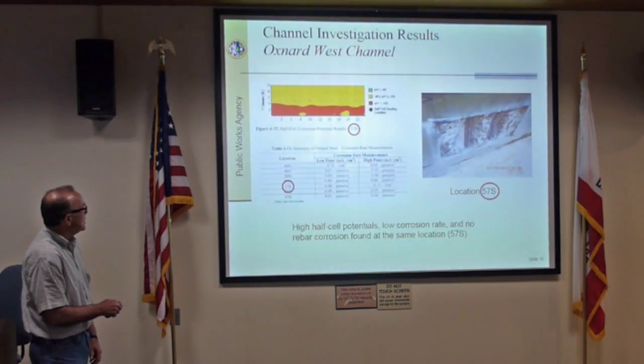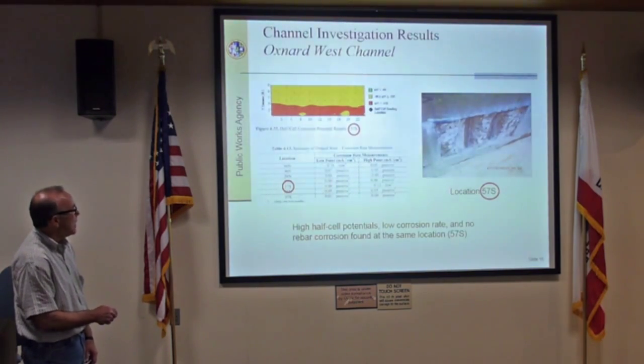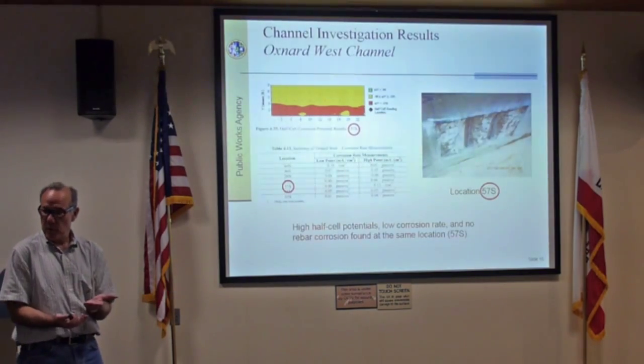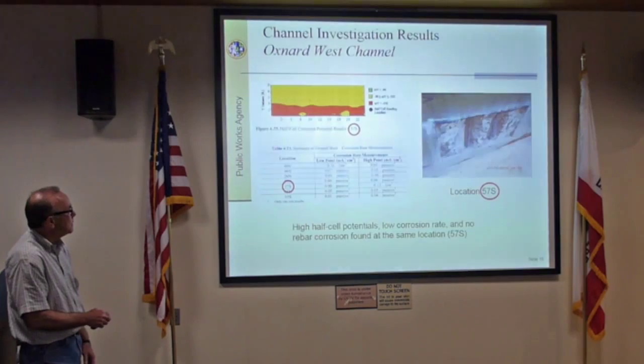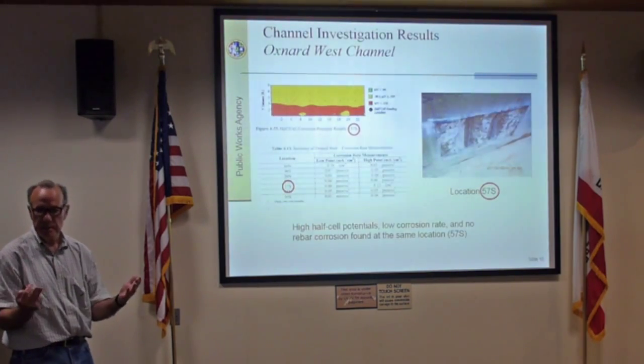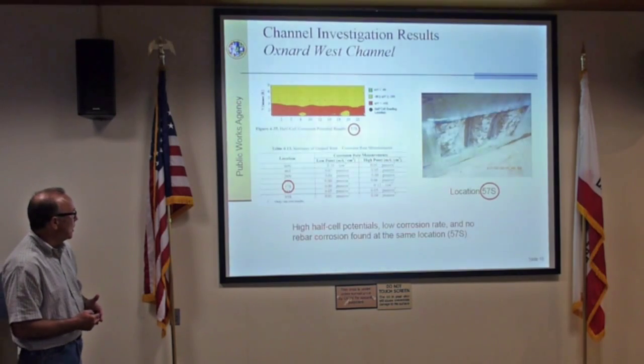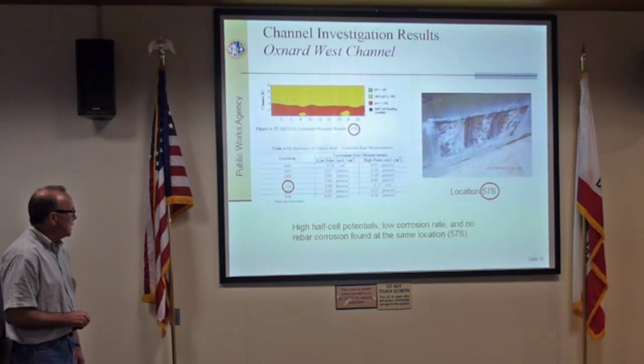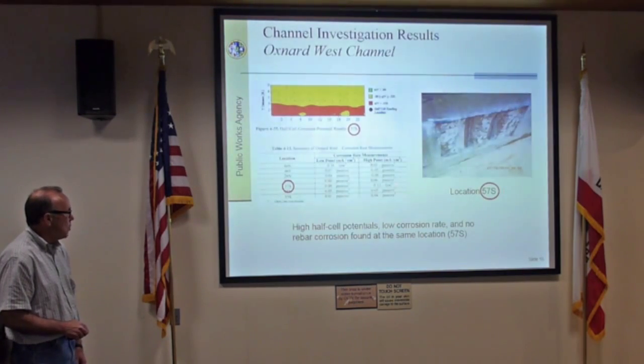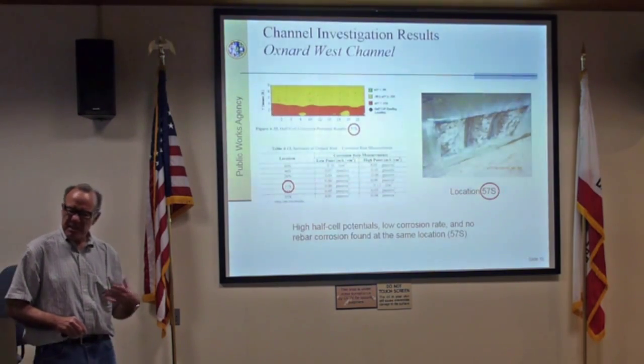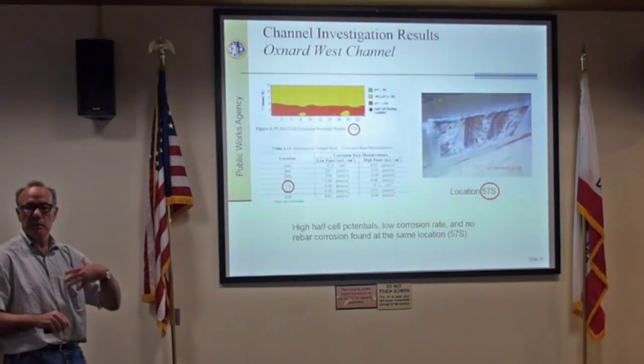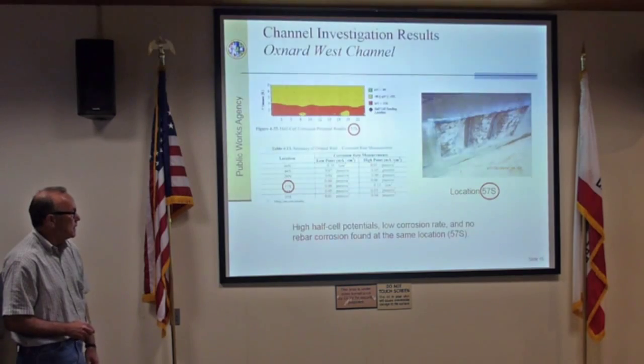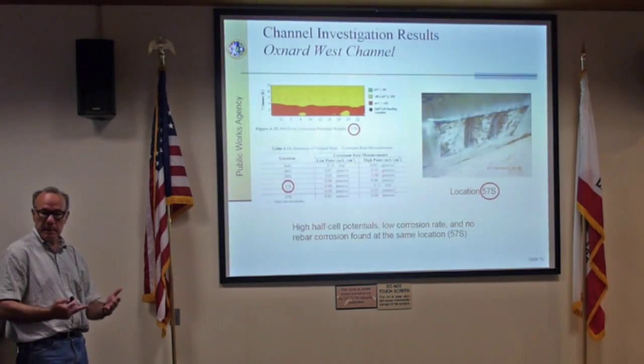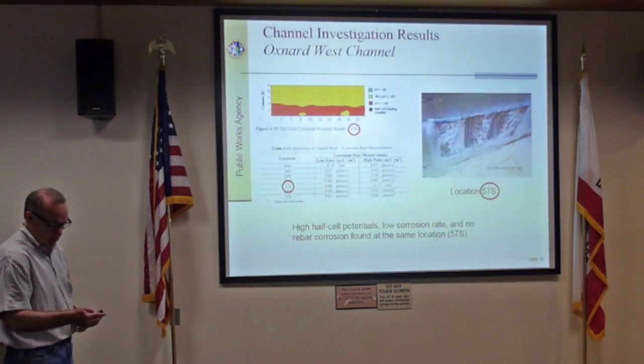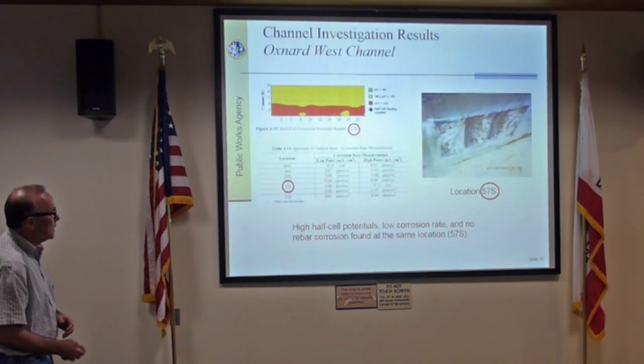And so you can see we've got a zone here near the very bottom that's the hot spot, where that joint is. Everything else is inert. We haven't had much moisture penetration. It's been pretty inert over all these years. We also did some corrosion rate tests. The highest value we had is 0.13 in terms of corrosion rate. That's a fairly low corrosion rate. So even though we had active corrosion, the rate of it wasn't necessarily overly aggressive. So we were able to detect the corrosion, but the rate wasn't high. When we look at it, there's a few hot spots in this area, but not a whole lot.